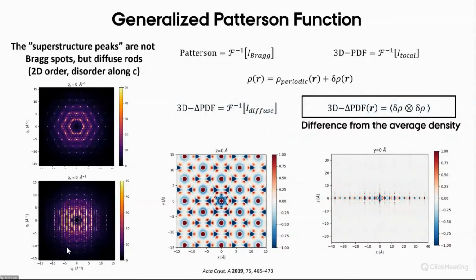I think most crystallographers know the Patterson function, which is the Fourier transform of the Bragg peaks, right? But if you instead Fourier transform the diffuse scattering, you get this other correlation function that we call the 3D delta PDF. The delta here is because we can write the electron density as a periodic density plus the difference to this periodic density. The diffuse scattering will then be the correlation function on this difference to the average density. When you do this on copper selenide, you get, in the plane, beautiful correlations to very, very high R values, whereas in the c direction, perpendicular, they die out very, very fast. So clearly these rods are due to the disorder along the c axis.